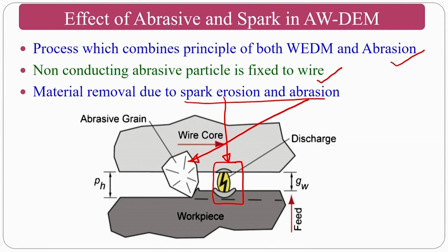Okay. So for the people who have not understood, or if you were not there a few minutes back, the mechanism is clearly explained here. Because of the spark erosion in this area, what will happen? Thermal melting and evaporation takes place. Not only melting and evaporation takes place, this also conducts a lot of heat inside. Because of which the thermal softening of the workpiece will take place, and the abrasion action of the grinding wheel or the abrasive wire will remove material with very less normal forces. That is the beauty of this process. That is why the material removal will be very high if you increase the current. At the same time, if you increase the current, the normal forces will be very less.